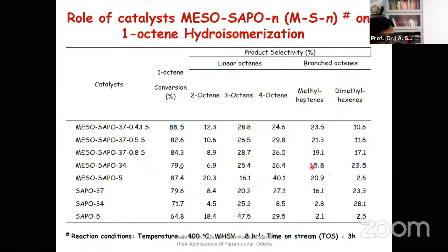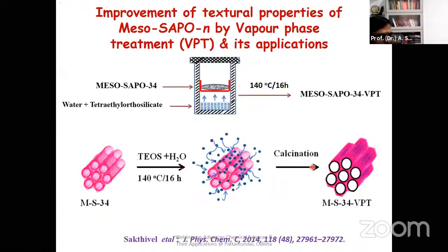Then we tried to improve the branched isomer selectivity by improving the strength of the acidity. How can we improve the strength of the acidity? Normally, the material we prepare will have some porous nature or some defect sites. These defect sites can be controlled by treating with tetraethyl orthosilicate, that is additional silica, and then we can get defect-free materials. Once the materials are defect-free by introducing the silica, we can have more acidity, which will be helpful for improving the isomer selectivity.